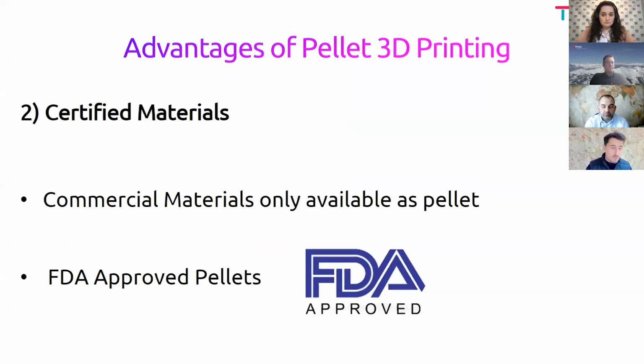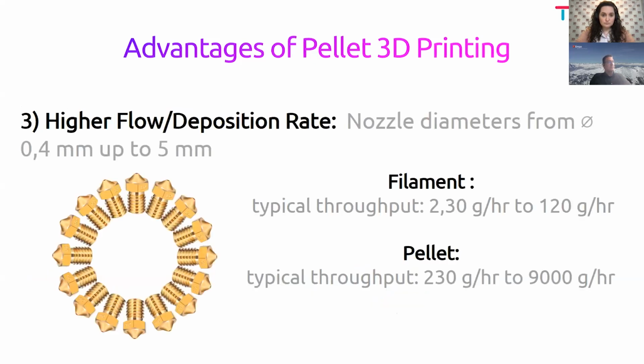And among these pellets, we can highlight certified and also FDA-approved materials. For some fields, such as tissue engineering or the biomedical sectors, the use of FDA-approved, chemical grade, biocompatible materials is required, and currently they are only available as pellet. There is another advantage that we can highlight, and this one is a high flow and deposition rate. So the pellet feedstock allows for much higher deposition rates, and consequently, we can print bigger volumes, bigger parts. However, as the build rate increases, the ability to achieve the desired geometry and in some cases the surface